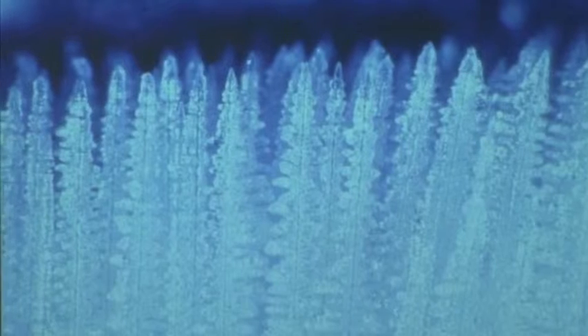If you go to the next slide, thanks, Nadia. So we had been doing work on metallic alloys. So this is a zinc-tin alloy. And the reason that we're using zinc is that it's hexagonal close packed, which is thought to be the crystal structure of iron under high pressure. So the dark here is the zinc-rich phase, and the light is the tin-rich phase. And so these are also dendrites. They don't have all the little side branches and quite as beautiful a structure as the ammonium chloride crystals do, but it's a similar sort of thing.